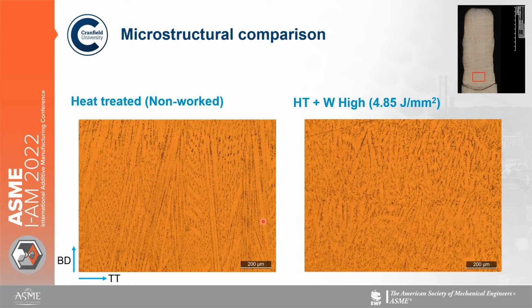And then at the very bottom of the sample, it's probably the clearest image to see this, but you've got very straight orientated grains compared to our worked material. It's difficult to make out some of these dendrite lines.